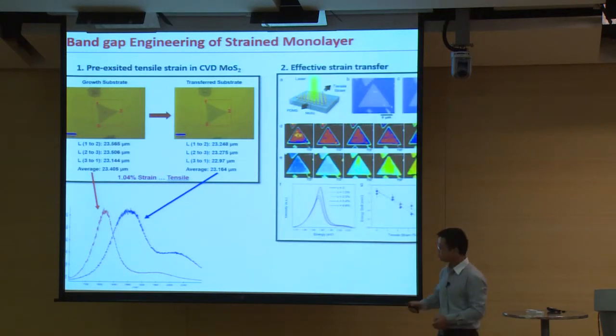And also, another problem is how much strain can be transferred from the substrate to the molybdenum sulfide. So here we put the molybdenum sulfide on the PDMS, and we're applying a force along this line. And actually, the molybdenum sulfide has been deformed. And then at the same time, we collect the PL mapping for different tensile strain from 0 to 5%. And we do see the shift of the PL peak. But definitely this does not correspond to the 5% strain. So only part of the strain can be transferred from the substrate to the molybdenum sulfide.